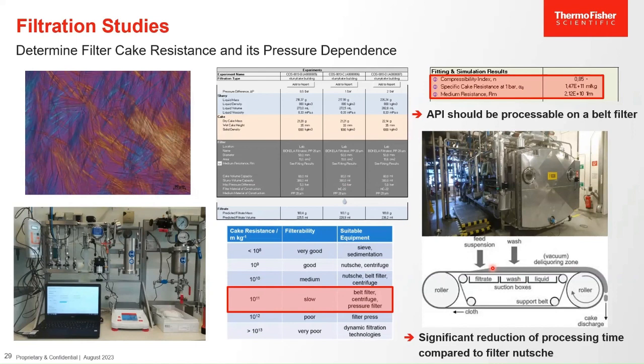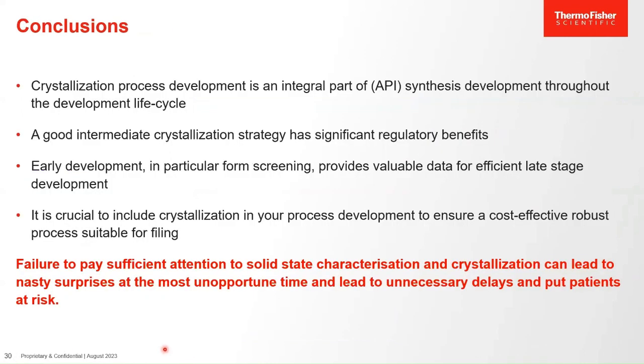And with this, you can rapidly decrease your processing time. We have had examples where we've reduced processing times from 3 weeks on a filter nutsche down to 3 days using a belt filter. Now, this may still seem a poor comparison, but a large fraction of those 3 days were actually subsequent washes of the material off the belt filter and not the filtration on the belt itself. That was considerably faster. And with that, I come to the end, and I'd like to summarize the presentation.